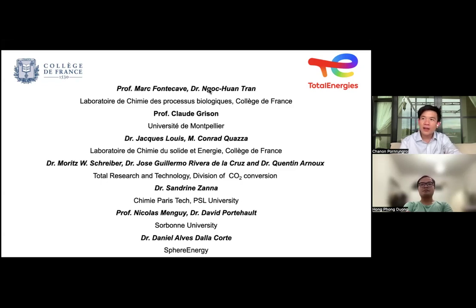And I have to emphasize that all of these results are done at industrially relevant current, so more than 0.1 amp per square centimeter. That's very impressive because I myself only work with 1 or 2 or maybe 10 milliamp per square centimeter. So that's about an order of magnitude lower than what Hong is doing.